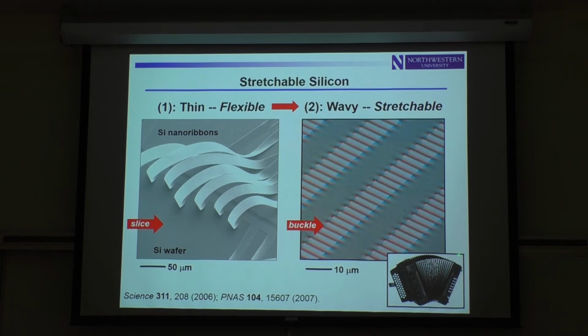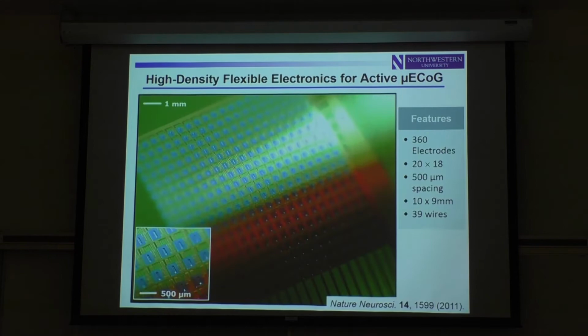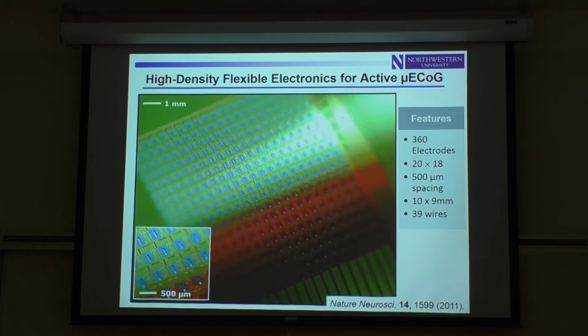So I can take this structure and I can stretch it out without breaking the silicon, because I can trade off in-plane deformations for out-of-plane dimensional change. So I stretch this thing, the amplitudes of these wavy structures go down, the wavelengths go up, in a way that has a purely elastic effective modulus. So that's the concept. It turns out you can do a lot with those basic ideas in mechanics and materials and composite design. I won't go through any more details around how you take those ideas and build them out into systems, but instead just transition into the final systems to give you a sense of what's possible.